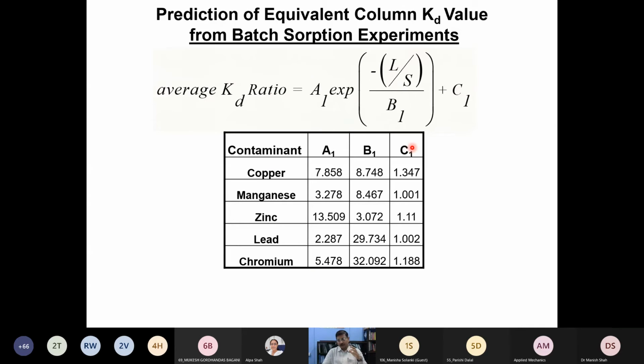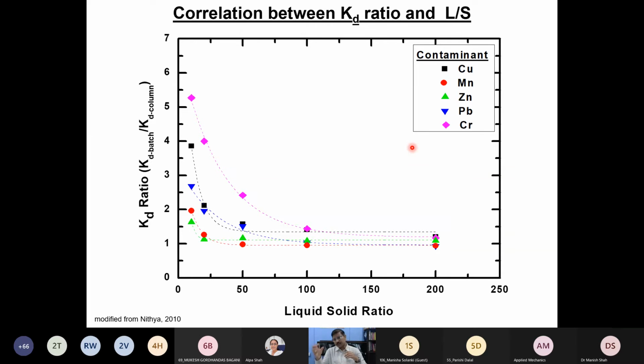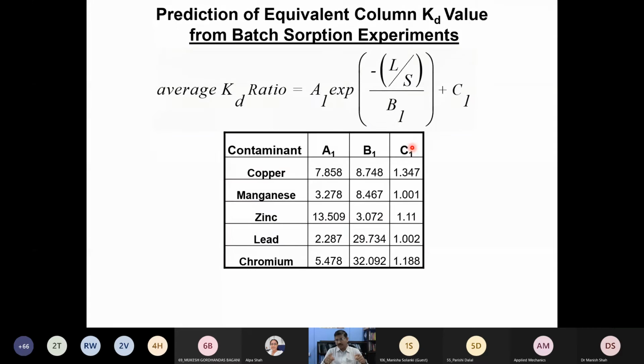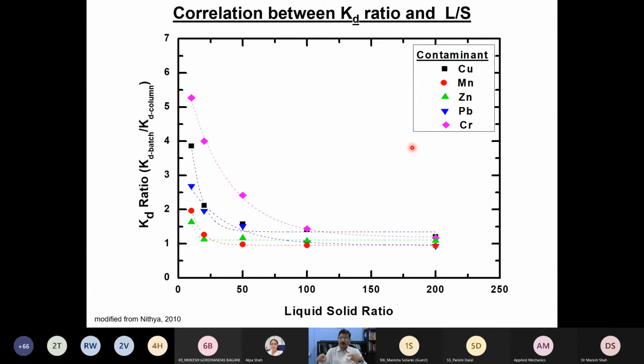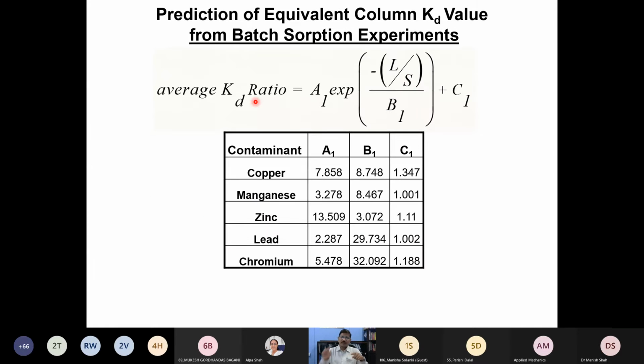So what I want to show you here is that you conduct a batch sorption study, which is very simple. You don't need to conduct a column flow through experiment, but by using this kind of empirical relationship, you get the KD ratio. That means the KD ratio is basically batch versus column for a given liquid solid ratio. Then you get a constant value. Once you have a constant value, you convert your batch sorption KD into column sorption KD. So effectively, you need not conduct a column flow through experiment, which is very time consuming. You conduct the experiment in a batch, and then by using the methodology proposed here,